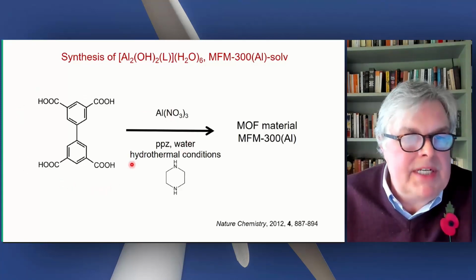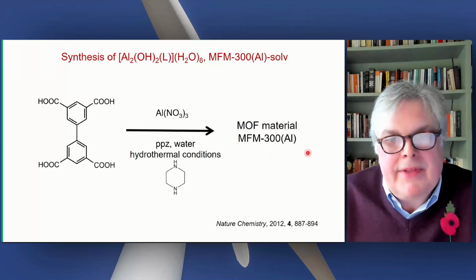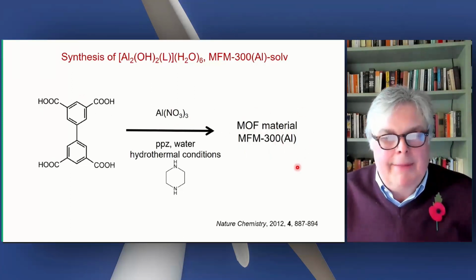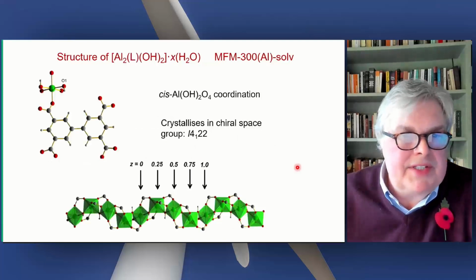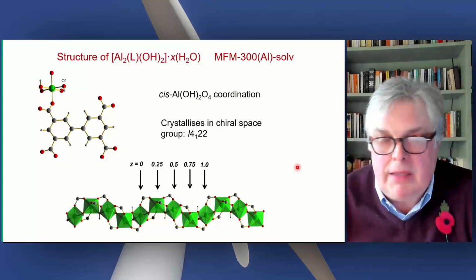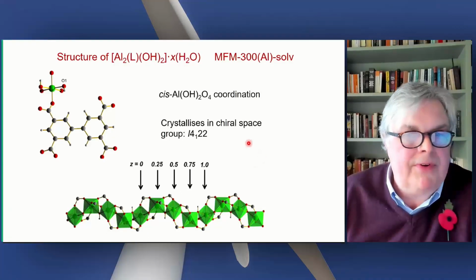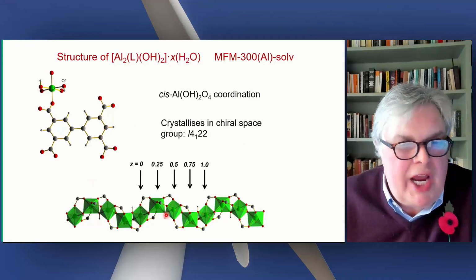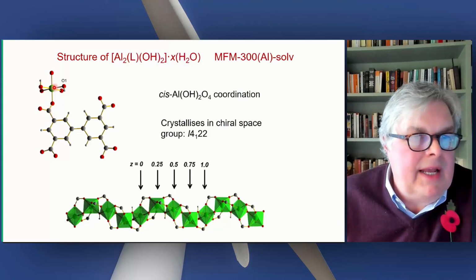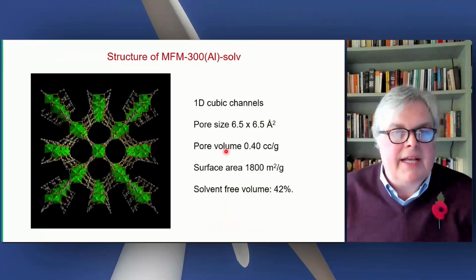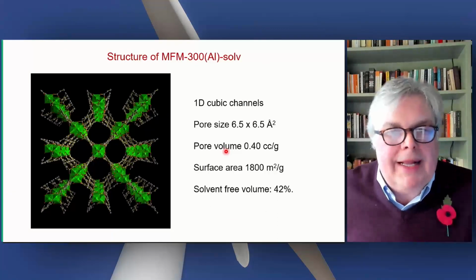We can make this material in multi-kilogram scale very cheaply. And we can make this MOF material, MFM 300 aluminium. So the synthesis we can scale up as well. We can make multi-kilogram quantities of this MOF. It forms a very nice chain structure because the aluminium coordinates to the carboxylate, and other aluminium is here. So this is the chain, and the chains are bridged to give this very nice 3-dimensional cubic lattice.